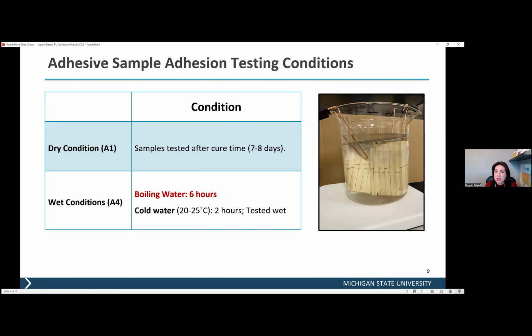When we prepare the samples, we need to test both dry adhesion strength and wet adhesion strength. Based on the ASTM requirements, after we make the CLT samples, we need to wait 7 to 8 days, almost 1 week, before we can measure the adhesion performance. This is the time for the adhesive to be fully cured.